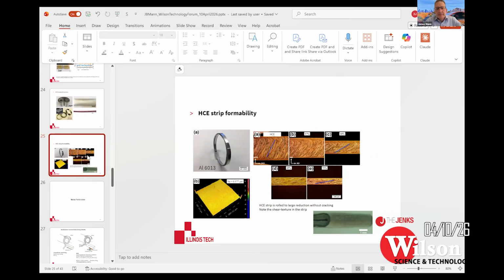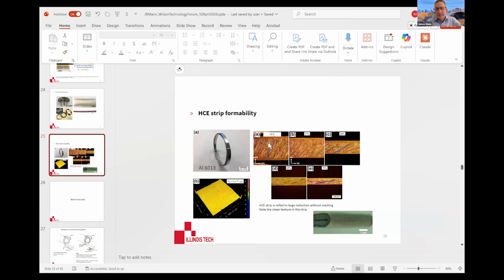Here's a series of images. This happens to be a strip of aluminum in picture A, and you can see the series of images on the right-hand side. The first image is what's called HCE, that's hybrid cutting extrusion. You're asking about the uniformity through the thickness. You can see at the edges of the strip, the strip walls, if you want to call it that, the top and bottom of the strip, the shear imposes a little bit of a flow orientation at the faces of the strip. And as that strip is rolled, you can see that gets a little bit more pronounced. But it's a very subtle change in the shear flow at the faces of the strip.